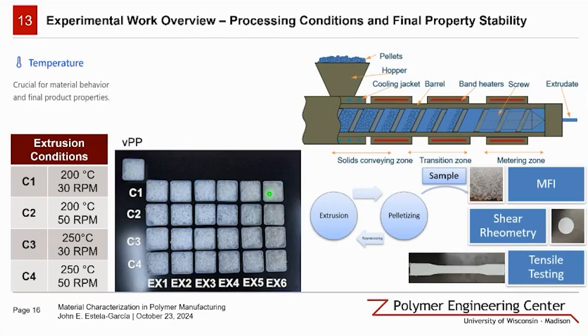So temperature is our first variable. It's not just about melting the polymer. It's about finding the spot where we can process the material effectively without causing unnecessary degradation. If it's too hot, we risk breaking down the polymer chains. If it's too cool, we may not achieve proper mixing and homogenization. Then we have screw speed. It's not just about how fast we can push the material through the equipment. The screw speed affects how well the polymer melts, how thoroughly it mixes, how much shear stress the material experiences, and all of these factors play into the final properties of our recycled material.